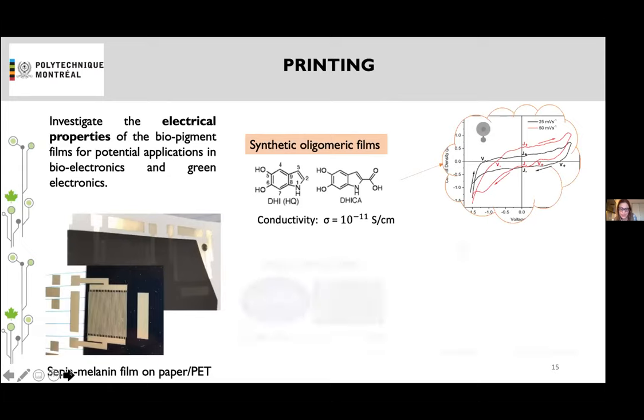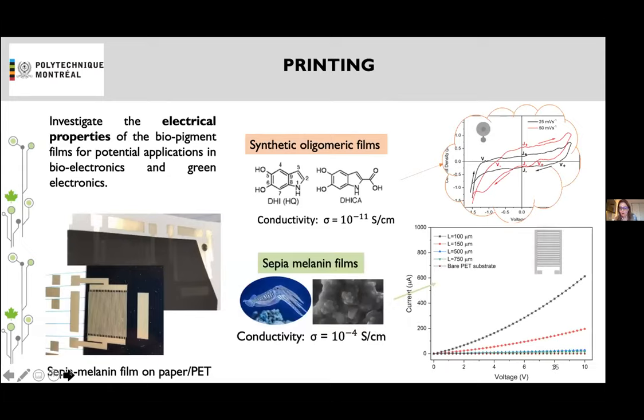So the point is that at the end of the day, our layer deposited by flexography over silicon dioxide, that is typical in microfab, or PET or paper, is a super homogeneous layer with a conductivity that is about seven orders of magnitude higher than when we go with the synthetic building blocks deposited over very tedious deposition approaches. So it looks like the binder that we need to formulate the ink to print over large area